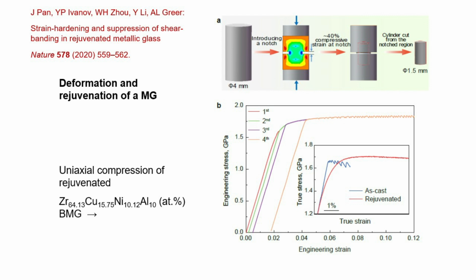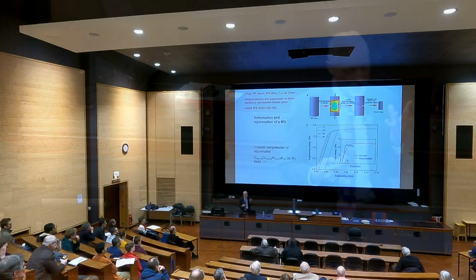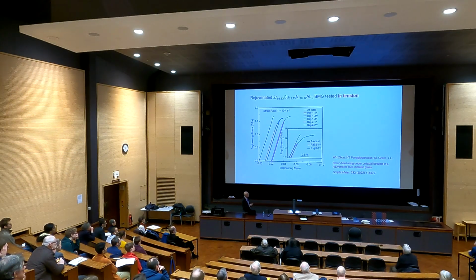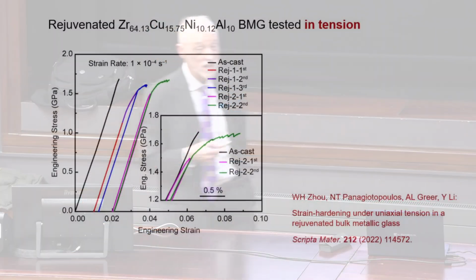And here you have classic strain hardening. Loading, unloading, reloading, resumes at the same point, gets harder. You'll say I'm cheating because that's in compression, and the real test is in tension, but it does the same in tension. So we have a strain hardening metallic glass.